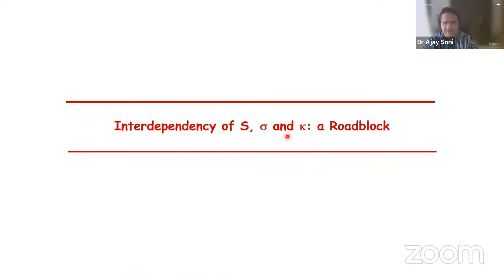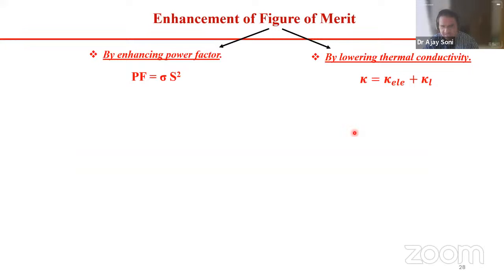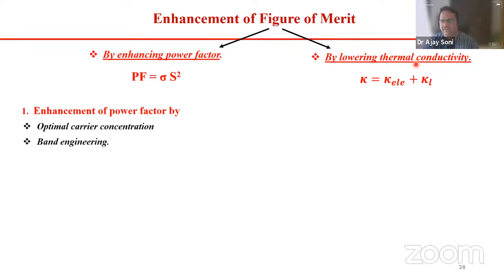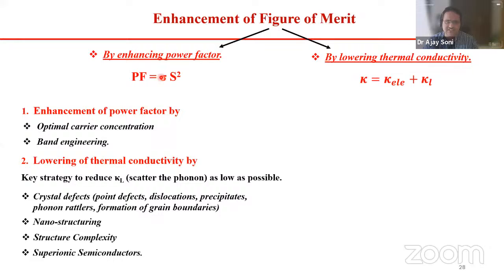So this interdependency of these three parameters, the Seebeck coefficient, electrical conductivity, and thermal conductivity, is a roadblock for these materials. But what you want is a material with a very high thermoelectric figure of merit. So you need to enhance the power factor, which is the numerator of the equation, and lower the thermal conductivity. You need a material with a higher electrical contribution, while it has poor thermal conduction.